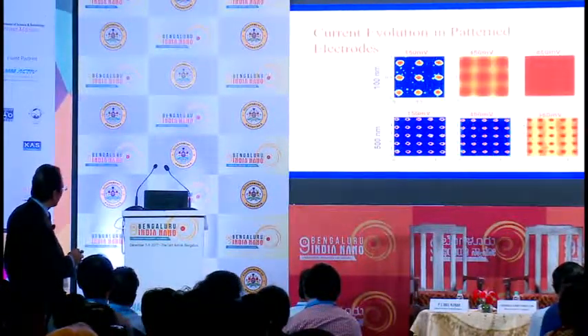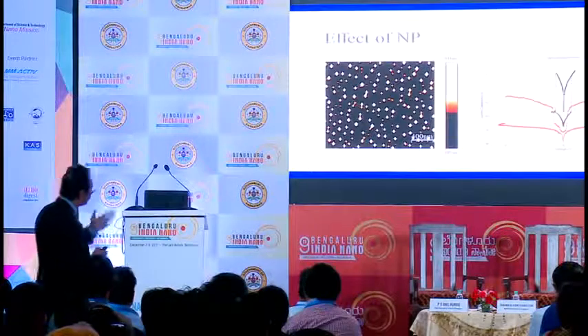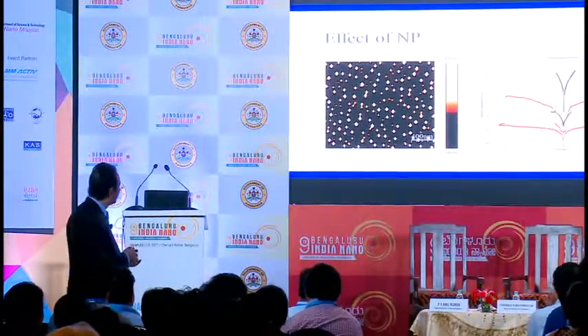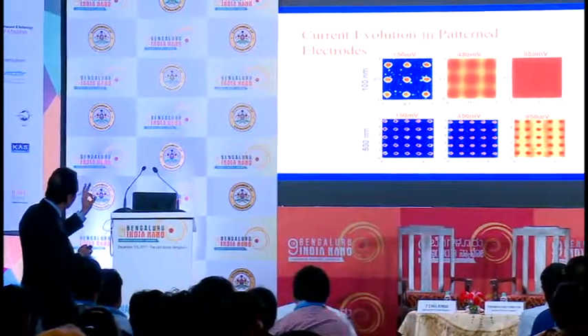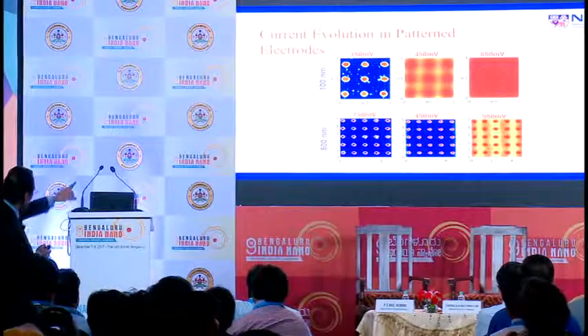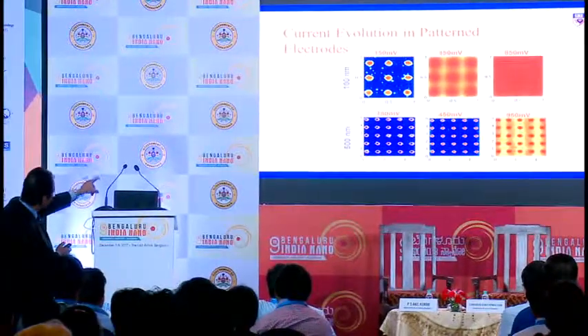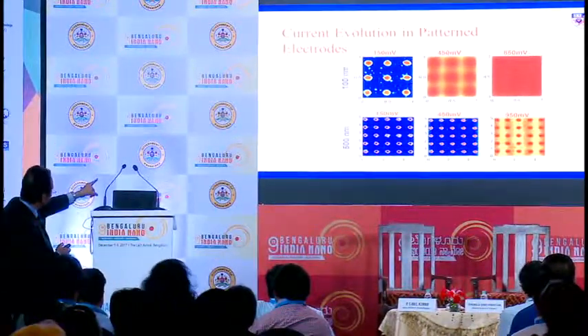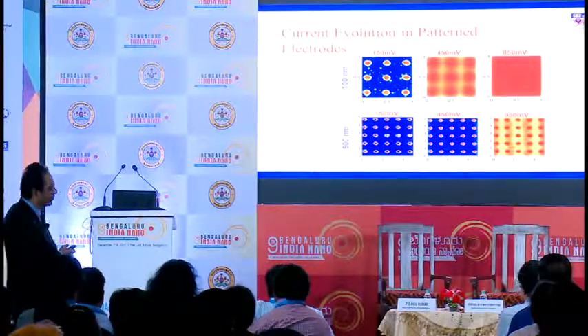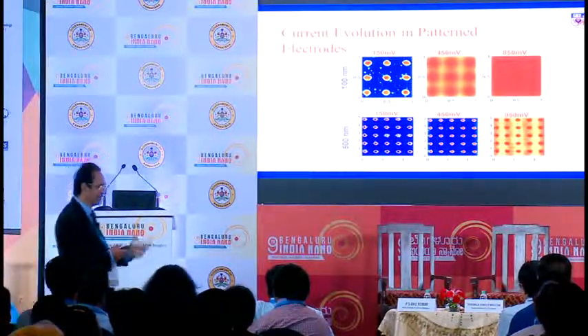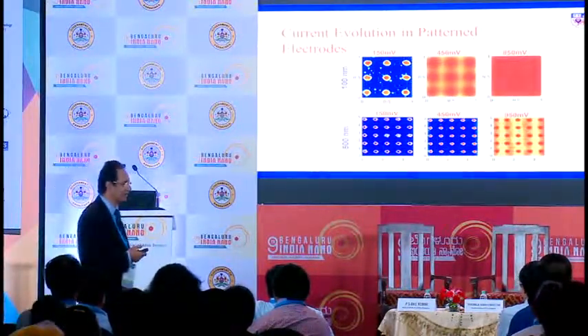So I asked the question, okay, well, maybe it's a local enhancement of the field. So we got our friends at NIST to make small electrodes for us. And this is essentially a 100 nanometer diameter electrode. And you can see at 150 millivolts, this device is completely switching on. So if you make the electrode even smaller, they'll probably switch on with even smaller voltages.